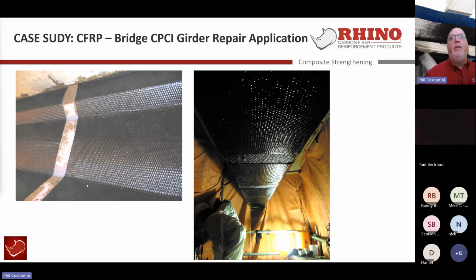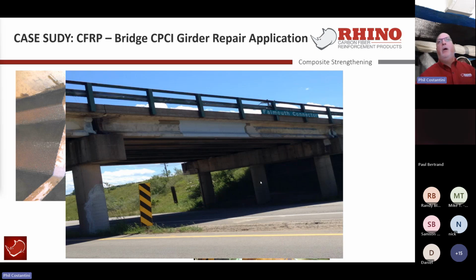We got our high strength requirements that the EOR allowed us to continue with our U-wrap application and reinforcement in those areas. But this is the type of hoarding, even though it wasn't done in the dead of winter, we still had to make sure we had perfect ambient temperature for the application of our epoxy to ensure a quality repair and to make sure that the concrete is still allowed to cure and dry properly, and then eventually introduce the final stage, which is the architectural UV protective waterproof coating. So that's the final repair there.